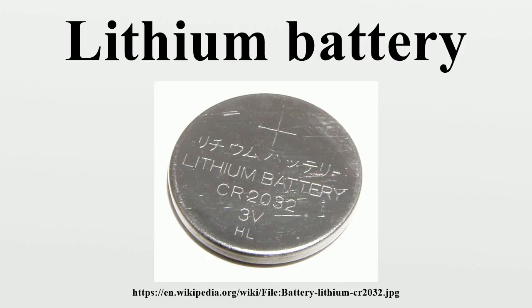Safety issues and regulation. The computer industry's drive to increase battery capacity can test the limits of sensitive components such as the membrane separator, a polyethylene or polypropylene film that is only 20 to 25 micrometers thick. The energy density of lithium batteries has more than doubled since they were introduced in 1991. When the battery is made to contain more material, the separator can undergo stress.